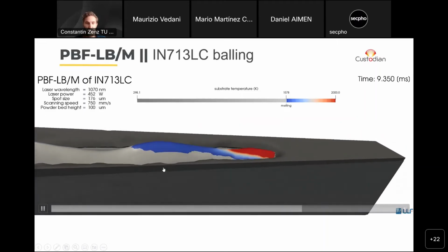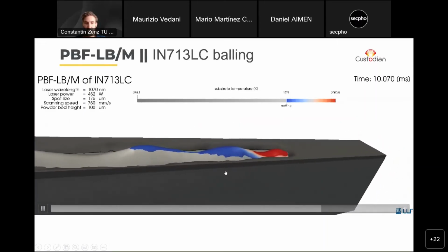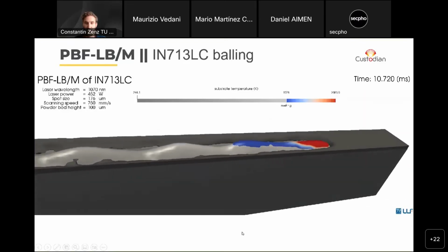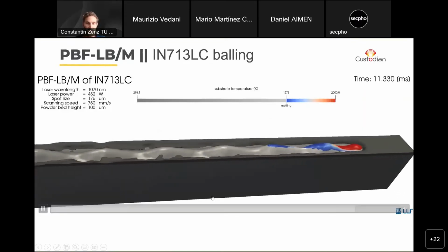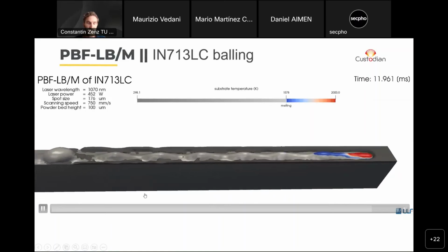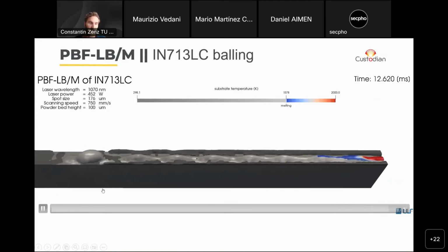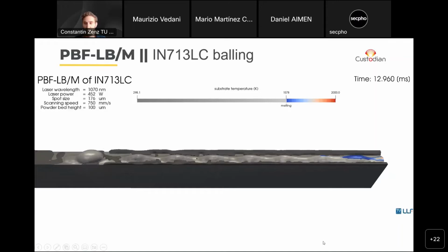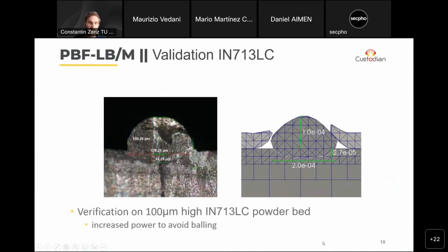So we end up with a similar structure like we saw in the experiment on the previous slide. So this is an issue that is related to surface tension on the liquid surface, which is pulling these spheres together, and a lack of wetting of the underlying substrate. And by increasing the power a little bit, it was possible to achieve a good cross-section and good results both in the experiment and also in the simulation.